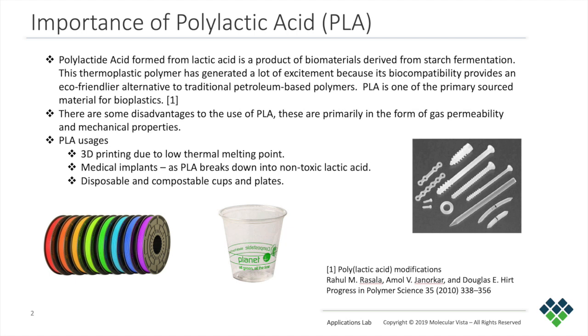decompose well. Now there are some intrinsic disadvantages to PLA by itself, and these primarily are in the form of gas transmission through the material and the mechanical properties. So they tend to be a little bit too soft, the rigidity is not there, and they tend to allow too much gas to flow through the material, which of course if you're using this for food storage or something of the like, of course that's not going to work well.